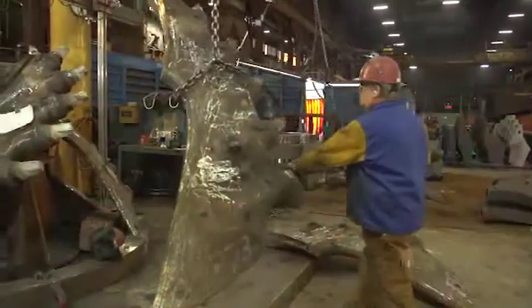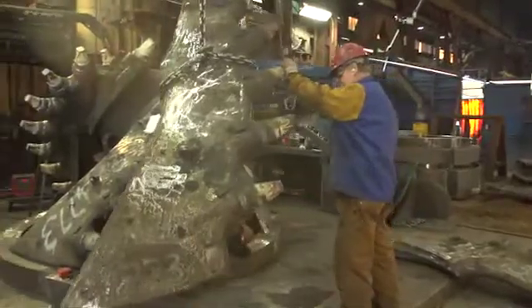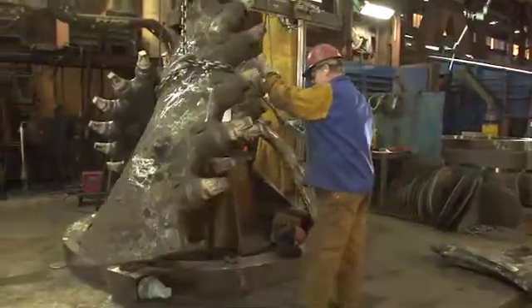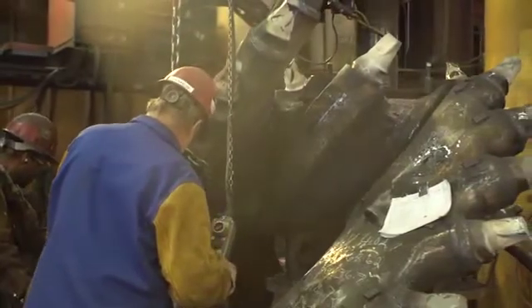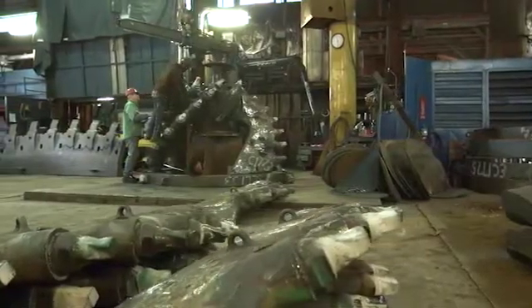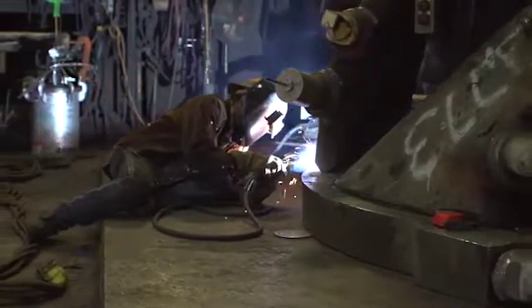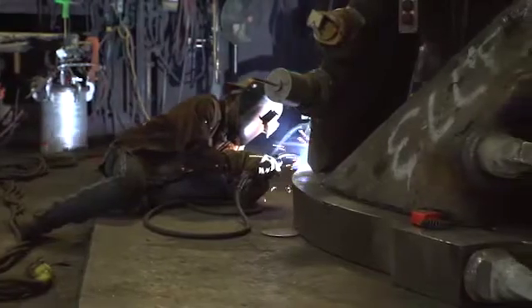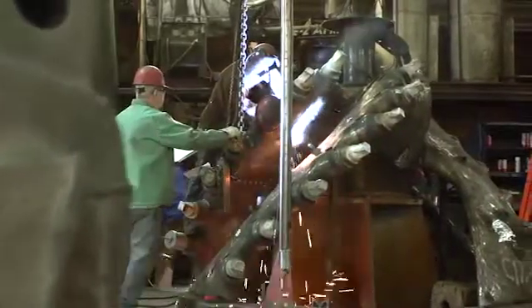Once the cooling is complete, a visual inspection for any imperfections is performed. To ensure a more detailed examination occurs, a magnetic particle inspection is also conducted. Sometimes, like with this casting, repair welds are needed to remove defects. Finally, the connection points of the cutter arms are ground to the proper size so that shrouds and points will fit snugly during field installation.